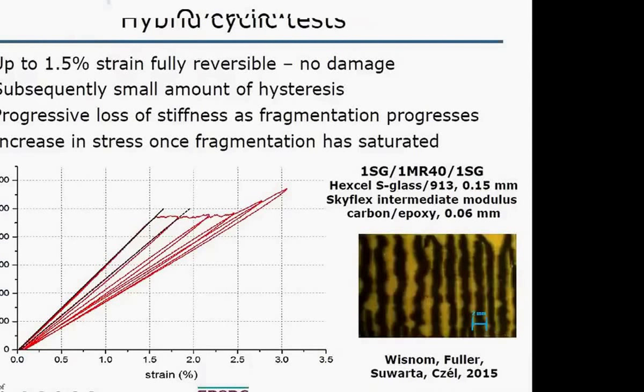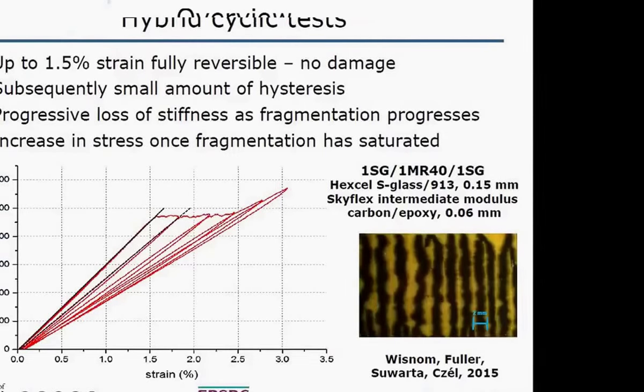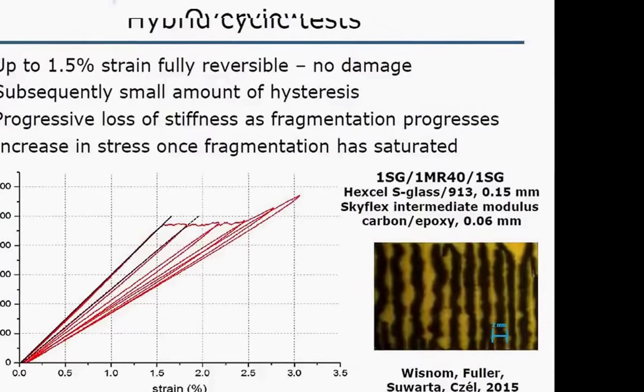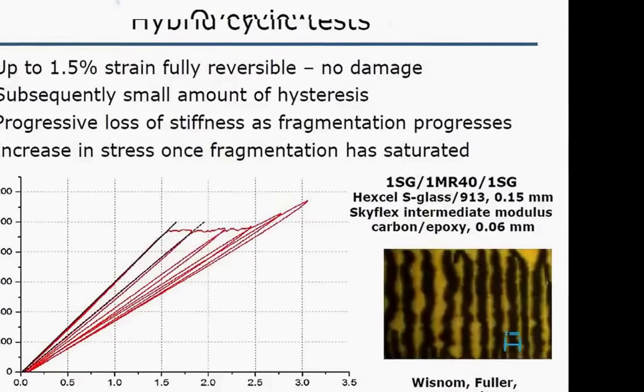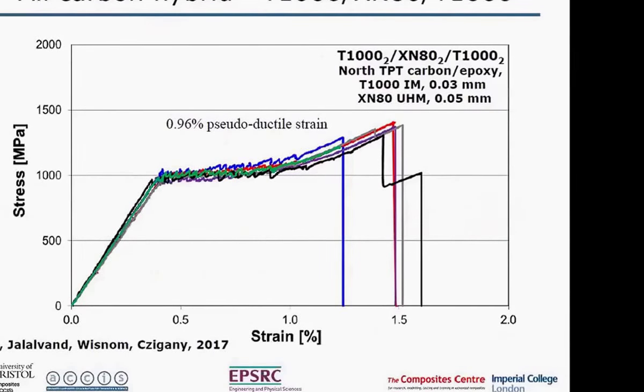So this is pseudo-ductility. It's not true ductility, it's pseudo-ductility because we've got damage, so we've got a reduction in stiffness and a little bit of hysteresis. And then when you get to the end of this plateau, where you've got fragmentation saturated, then the stress starts to pick up again. And this is where we're getting additional stress carried by the glass after the saturation of this fragmentation mechanism. So that's with the glass carbon.